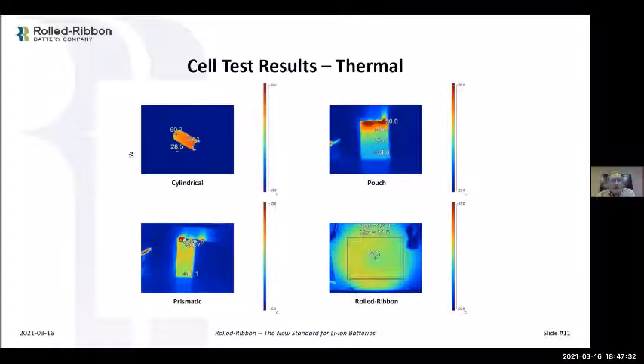You can see this in thermal images. Here we did thermography, infrared thermography on cells, and you can see how that works. Cylindricals actually have the worst thermal properties, not surprising. And so you can see they have all this heat, and the heat actually migrates. The tab comes out and attaches to the end of the cylindrical. So all the heat you see in the can actually coming from this thermography is the heat that traveled up that little strip, the tab, to the terminal, the tip at each end of the cell. And then the heat traveled from the cap on here back over the can. The temperature inside the can is actually 20 degrees C higher than the surface of that cell. And that's true for all three of the conventional cells.